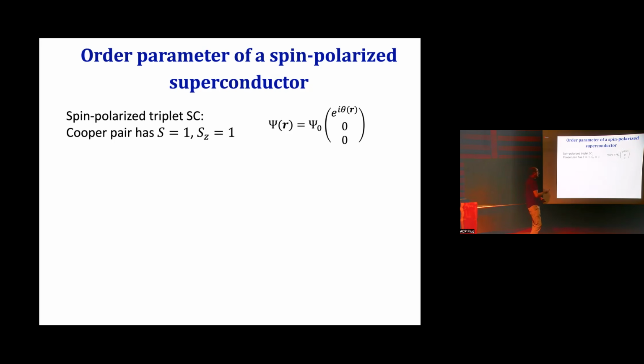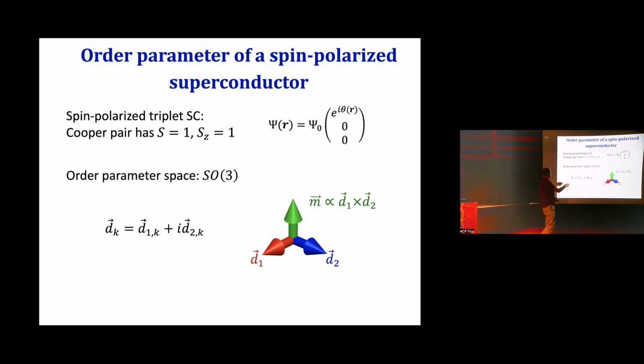And you can ask, what's the order parameter space? What do I need to specify the state of such a superconductor? And clearly, I need to specify a direction and a phase. And it turns out that this direction and the phase combine into basically a rotation matrix, a matrix in SO(3). It's an axis and an angle. It's like a rotation. For the experts, to specify the state of a p-wave superconductor, you can specify the so-called d vector, which is a complex vector. This type of state is characterized by the real and the imaginary parts of the d vector being perpendicular to each other, and the direction of the magnetization is a cross product, so perpendicular to both. If you didn't get that, that doesn't matter.